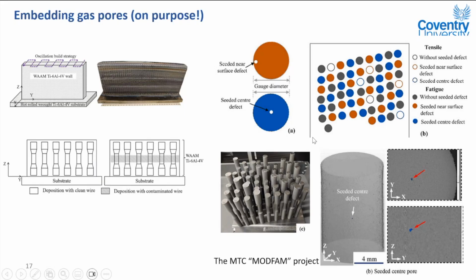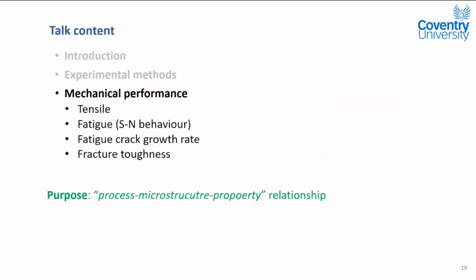And by computed tomography, it could confirm the pores are still there after the manufacturing. And this is an MTC-led project called MODFAM. So that concludes my methodology section. So now I'm going to talk about mechanical performance one by one. And the first one is the tensile, then fatigue crack growth rate.